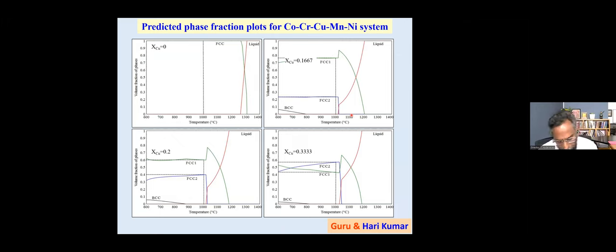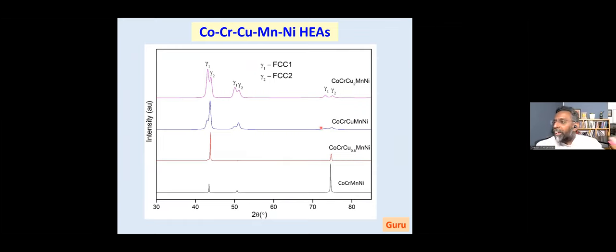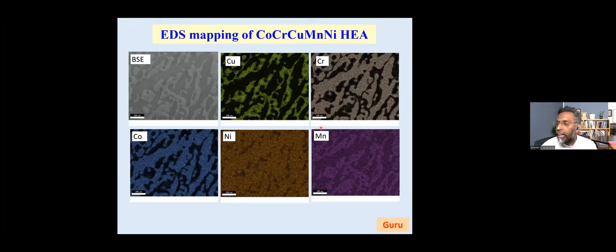And then we started looking at what happens if I add other alloying elements. For example, if you add copper to such an alloy, you start seeing that copper segregates, because copper does not dissolve into many of these elements. So it segregates and gives you two phases. One can see these two phases very easily by doing an elemental mapping to know where the copper is. You find that copper is in what is called the interdendritic region, compared to the rest of the elements which are all inside the dendrite. So inside the grain, all these four elements are there, whereas the copper is rejected out of the grain and goes to the grain boundary region. And that is something that can be proven.